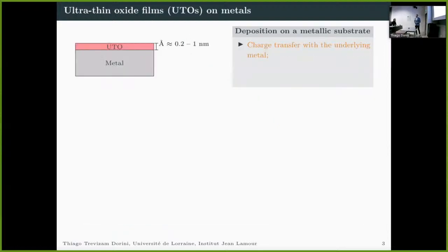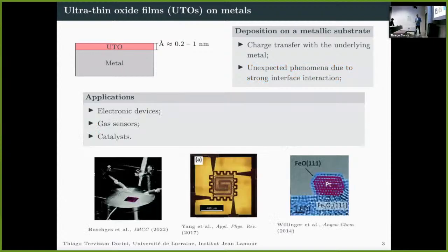And to be even more precise, the type of material that we'll be dealing with are ultra-thin oxide films when supported on a metallic substrate. So here, as you can see on this sketch, we have an ultra-thin oxide film in red of thickness of about 0.2 to 1 nanometer, supported on a metallic substrate. And as we all know, bulk oxide is usually an insulator or a semiconductor. But when you reach the ultra-thin film limits and you support it on a metallic substrate, there is a significant charge transfer between these two materials. And this leads to many unexpected phenomena that happen due to this strong interaction. And this kind of material has some really interesting applications, such as electronic devices, gas sensors, and catalysts.